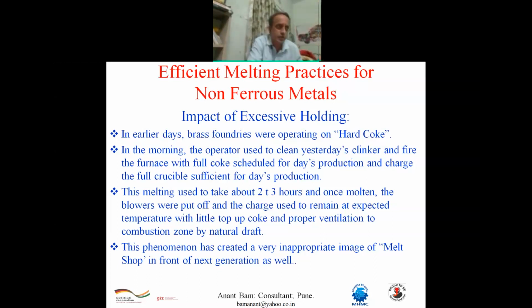For the first heat, it used to take about 2 to 3 hours, wherein the hard coke gradually catches fire and it reaches to the top. And once it is fully fired, the blowers were shut off and the vents at the bottom of the furnace were opened to allow natural draft. Hard coke has got this peculiarity that it does not require continuous excess airflow. Once it starts combusting, it continues and it delivers gradual heat.